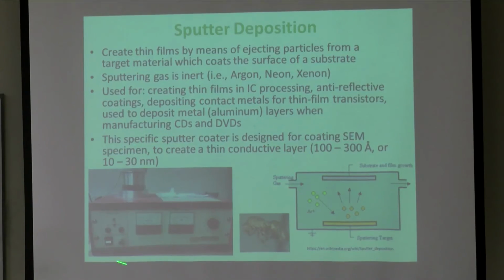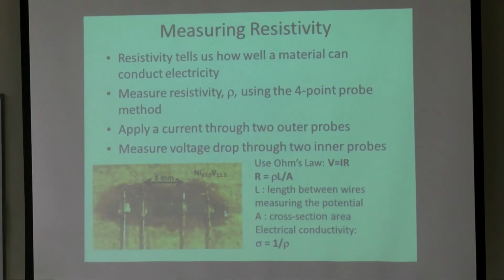So again, the sputtering device that we have in the lab next door was originally used for the SEM, especially if you don't have a conductive material in the SEM and you want to coat it with a thin conductive layer so you're able to take pictures and things like that. But it is functional. You can still coat up to, I think, 300 angstrom or 30 nanometers if you wish to do so. And I think pretty much I'm done.